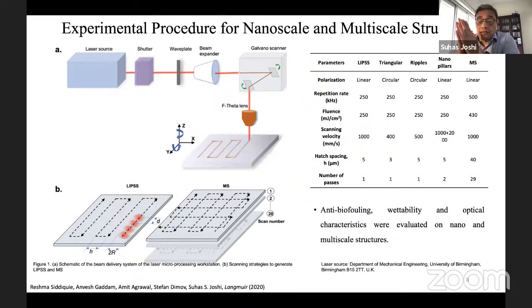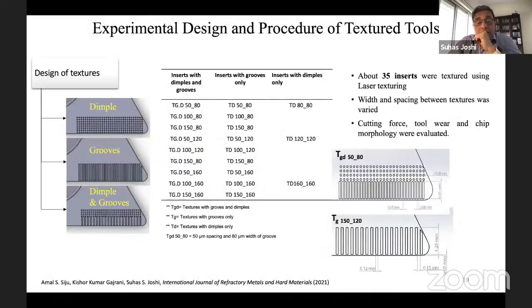In the third level, we did something called a hatching pattern on the work surfaces. So H is the hatching distance between the two lines when you are scanning the laser on the surface. And then you go for multiple scans, first, second, third, fourth, as many as 29 scans on the surfaces. And you will find that with the multiple scans, you are able to generate another extraordinary kind of structures on the surfaces. So I'll go to the first kind of structure. This is dimples, grooves, and dimples and grooves kind of structures.